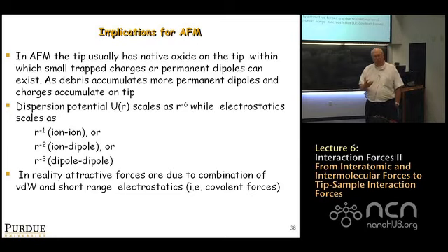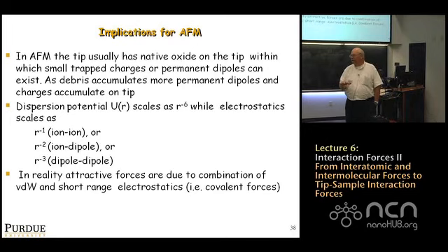So it wouldn't be surprising if you start scanning in the morning with the tip and your scans look good, and then as the day progresses, as the tip gets more contaminated, your scans start to degrade because of these electrostatic forces between tip and substrate that, in principle, we like to eliminate, right? Those forces are long range. If they're long range forces, then you have a very hard time getting contrast at the atomic length scale, which is one of the things that AFM is capable of doing, right? So you have to worry about that.